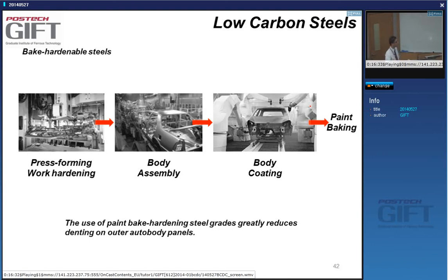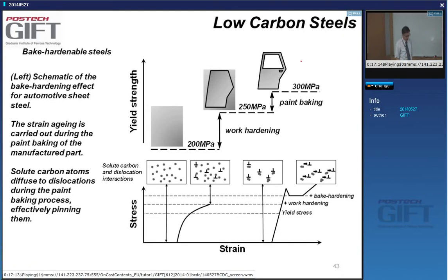Yes? So it will give you an annealing, basically low temperature annealing of your steel, typically 150 to slightly above 200 degrees, and of the order of minutes, 20 minutes, yes? So 20 minutes. And so that's actually a situation where we get aging in steels that can age. So this is the idea of this bake hardening steel.